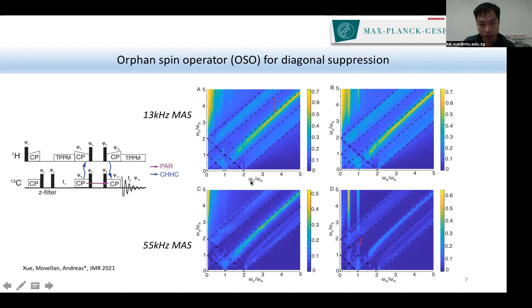The x-axis is the power we set on carbon or on nitrogen over the rotor period. On the y-axis is the power we set on proton over the rotor period. All these black dotted lines here are actually the CP conditions, n equals 0 and n equals +1, -1 CP conditions here. And the color-coded map here is our PAR power condition. So when we are at slower spinning and with a 90 to 100 ramp on the proton, we actually have the power on proton cover this length here, denoted in red arrows.